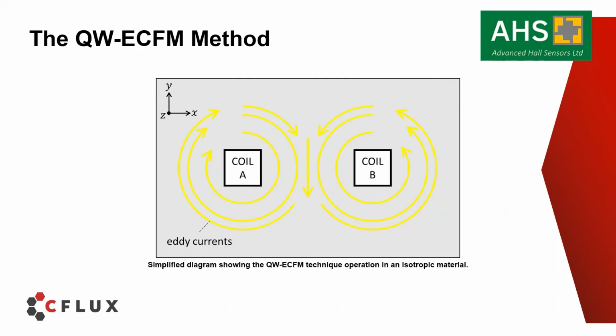Taking inspiration from the operation of alternating current field measurement, we have developed an electromagnetic NDT technique involving the use of a pair of illuminating coils to produce a linear region of eddy current. This setup has been designed to be used near DC through to 4 MHz, the optimum frequencies used dependent on the materials being inspected and the other NDT requirements and considerations. Perturbations within this linear region of eddy current are detected via the simultaneous measurement of normal and tangential components of magnetic flux density using 2 orthogonally aligned sensors.